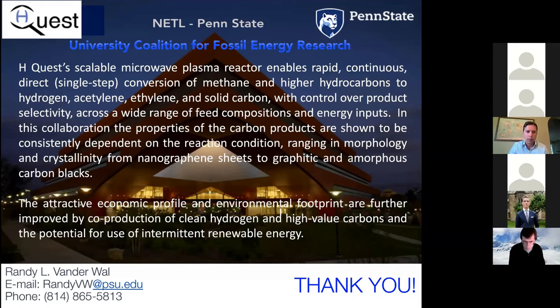From the standpoint, in other reactor conditions, and actually in one of our previously published papers, we have had much higher nanographene contents. I can't speak exactly to the percentage, but they have been far higher. And other reports in the literature also suggest far higher percentages of nanographene in the form of solid carbon. These conditions and processes under which it is formed are, well, I'll suggest highly non-equilibrium. And so there are many coupled parameters in terms of plasma intensity, concentrations, residence times, governing that relative phase fraction, if you will.